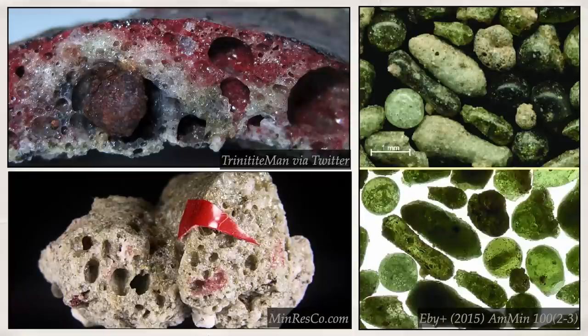There are a few other less common trinitite types, including red trinitite, which is still mostly green but has red streaks or red specks. The red is due to copper, primarily from the wiring of the bomb and also the tower. There's also black trinitite, which has lots of iron — mostly from the tower. Remember the tower was vaporized in the blast — it had to go somewhere. One sample photo has an actual blob of iron sitting on the top left, most likely from the tower. There are also beads and dumbbell shapes of trinitite, which formed as molten glass coalesced in the air during the blast and cooled enough before landing to maintain their shape, occasionally stretching into elongated forms because of centrifugal motion.